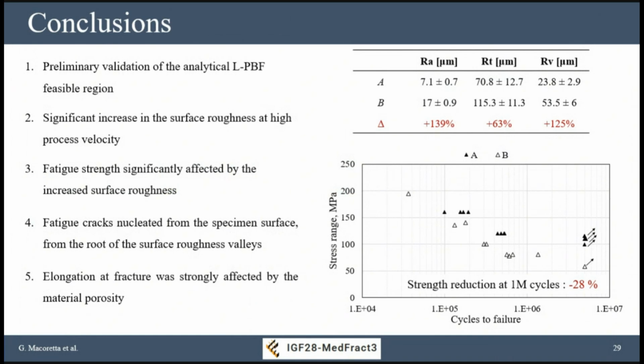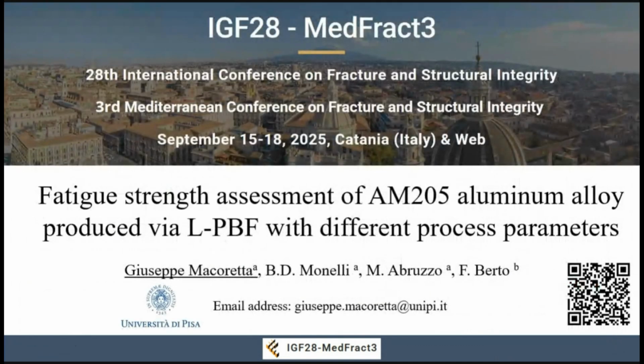Fatigue cracks, as I showed you, started from surface roughness valleys and defects, while the elongation at fracture was significantly affected and even more affected than the fatigue strength. Based on this, in the future we'll start rationalizing the data using an approach based on fracture mechanics, like the Murakami approach, dealing with surface roughness defects and considering them as the origin of our fatigue performance. Thank you for your attention.